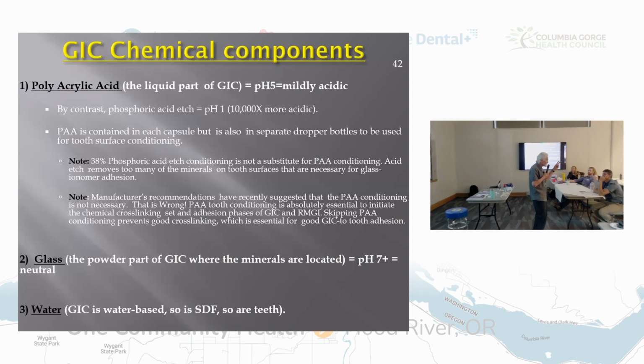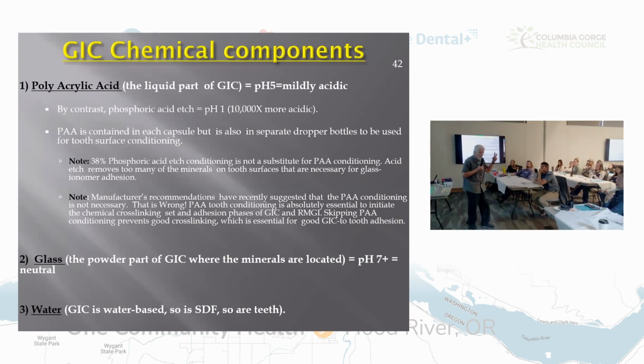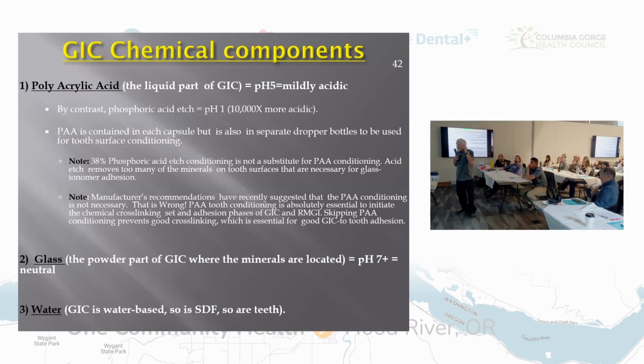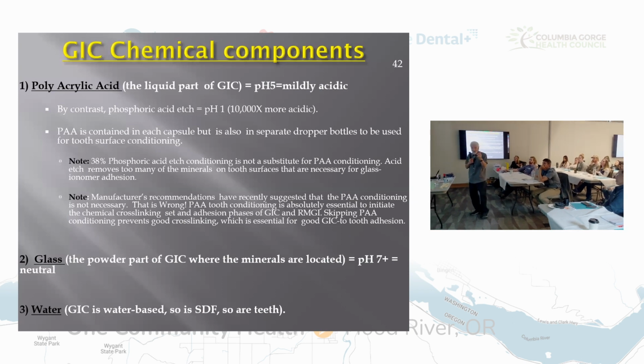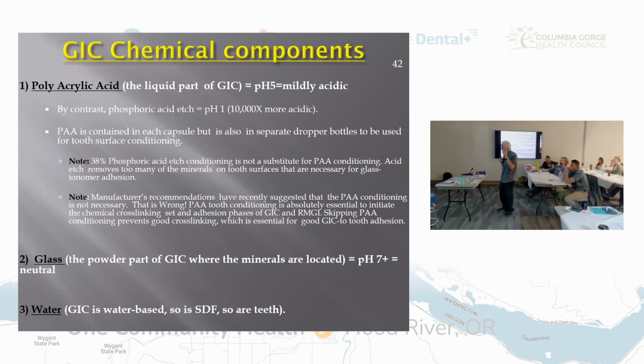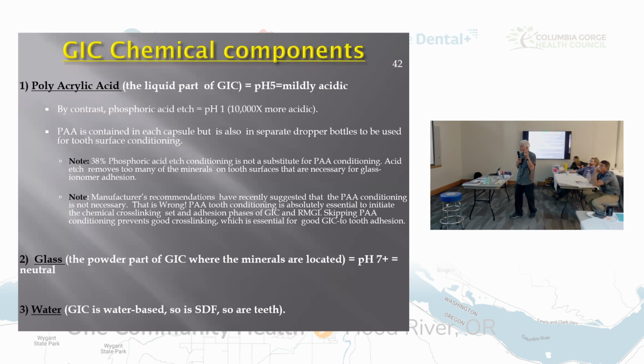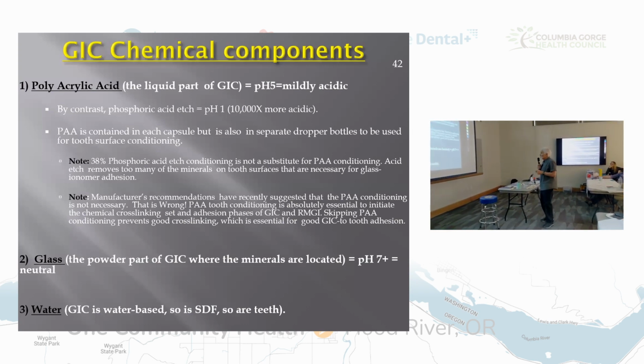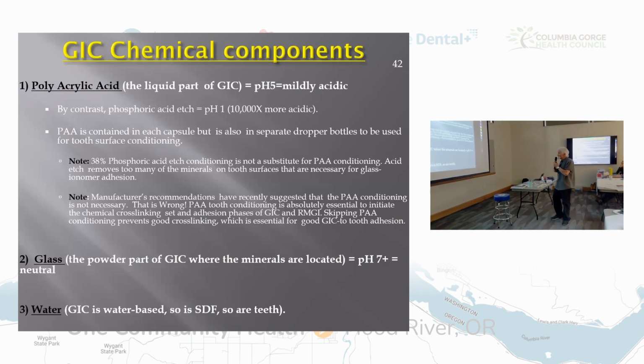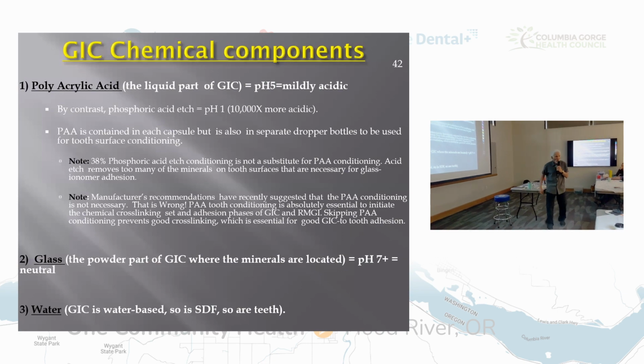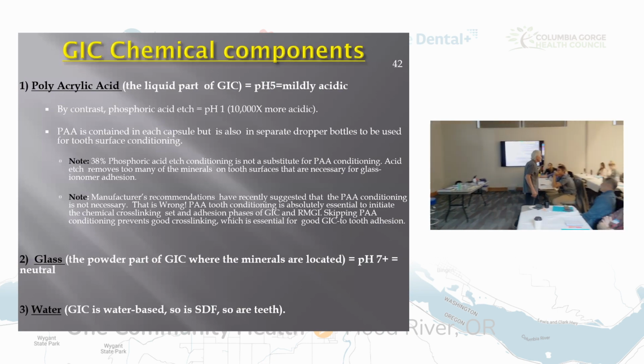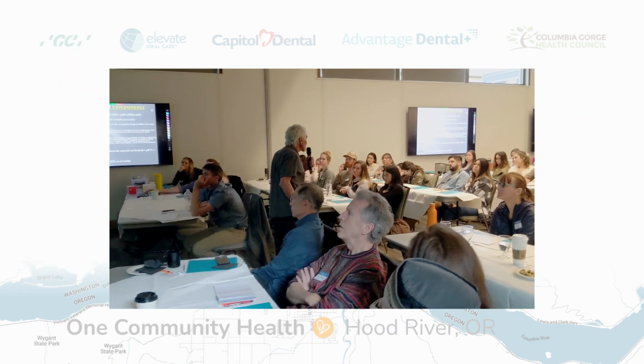We're going to talk about the set phases. It's the second set phase. Okay? An adhesion phase of glass ionomer and resin-modified glass ionomer. Skipping the polyacrylic acid conditioning will prevent good cross-linking, which is essential. Okay? Why do they recommend this? Because it skips a step, and they sell more material, and that's not okay.